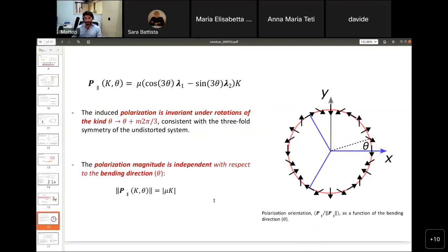We find, looking at the expression, that actually the polarization continuously rotates with the bending direction, and in addition is invariant under rotation of the kind m2π/3, where m is an integer. This is consistent with the threefold symmetry of the flat layer. In addition, we find that the polarization magnitude is actually independent of the bending direction.